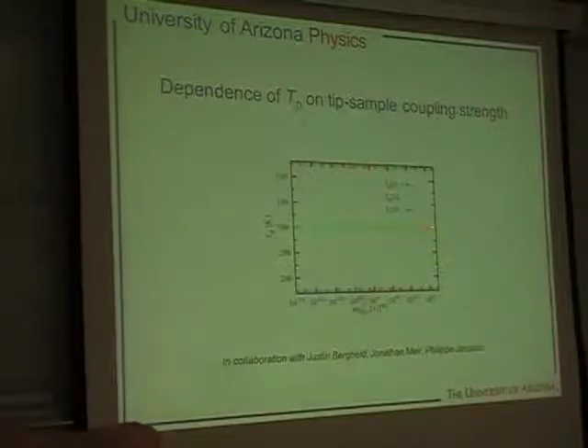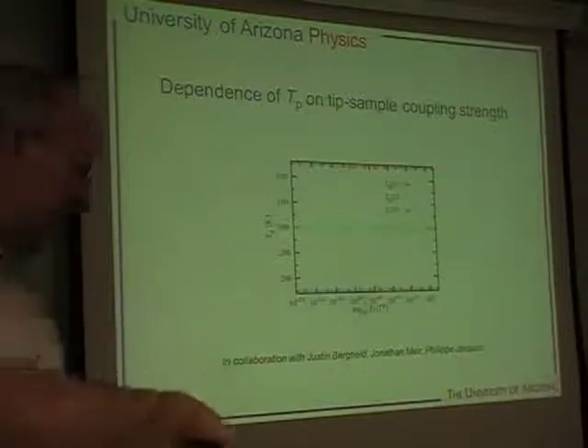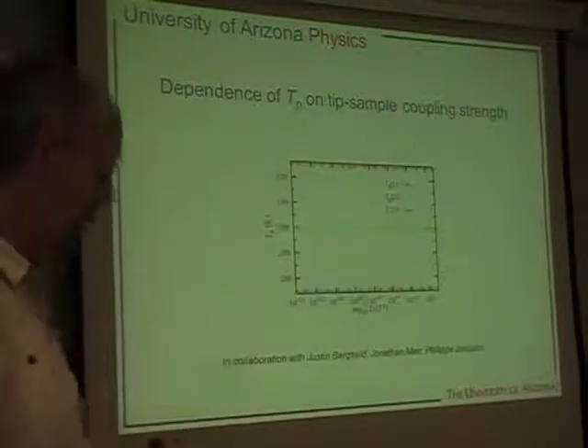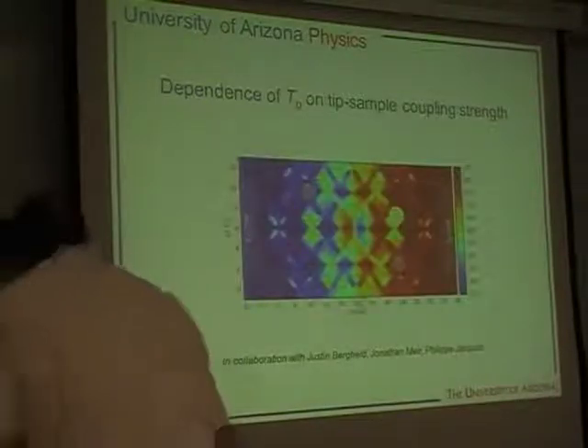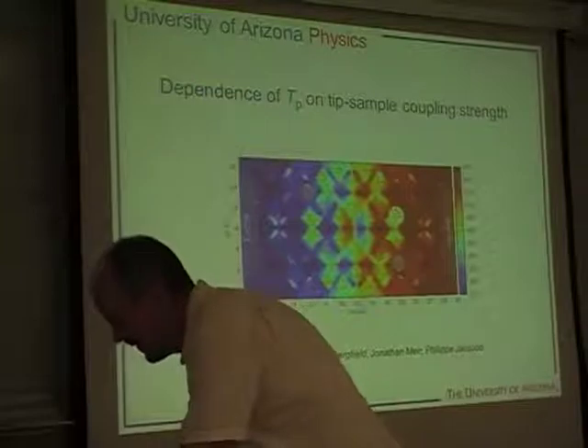Only when the coupling gets to be above an electron volt, then the widths, basically then the tip is coupling so strongly to the sample that it's starting to change the electronic structure of the sample, broadening out the resonances and everything, and then you get this effect. So I think you can kind of see that if we would go back. It might be easier this way.